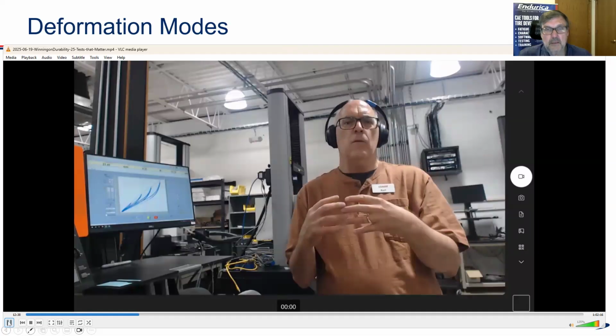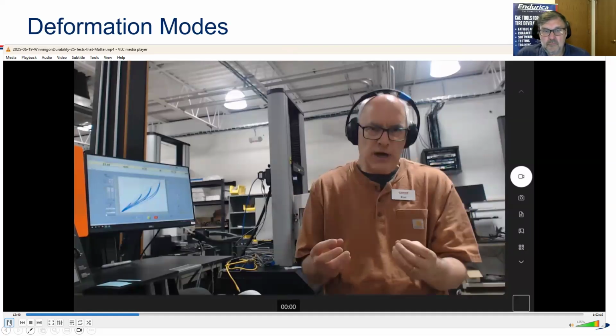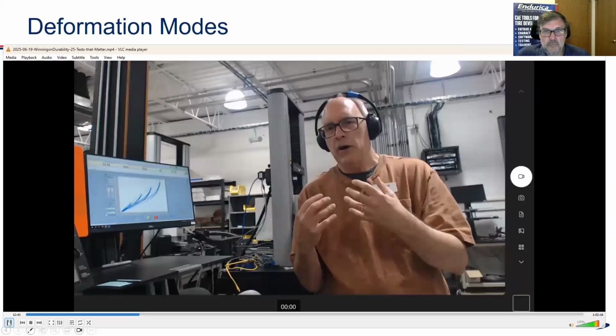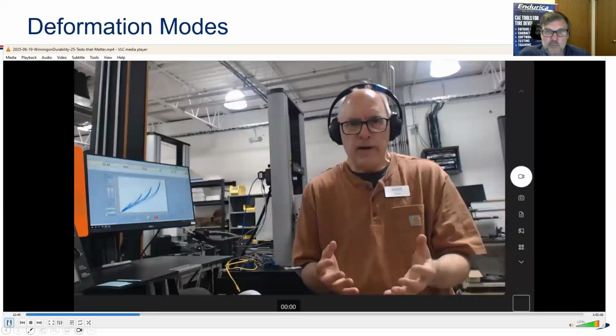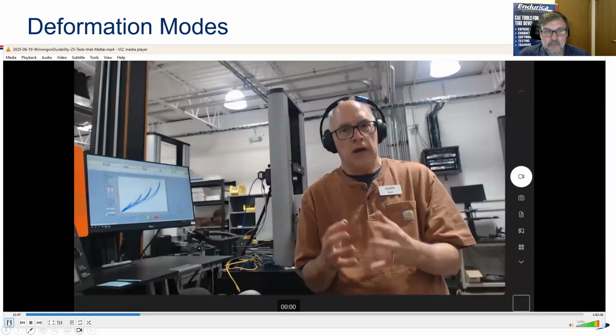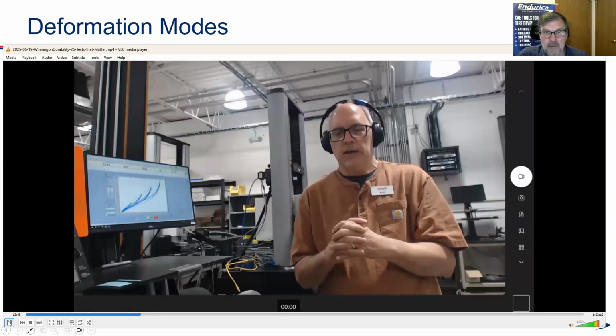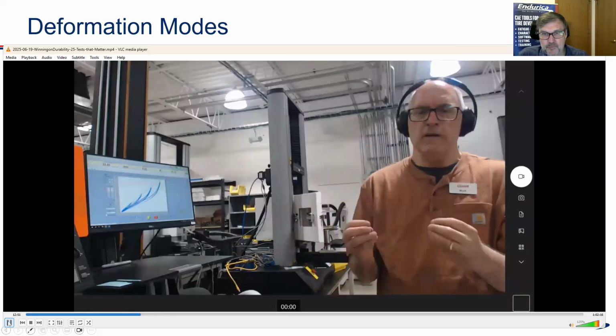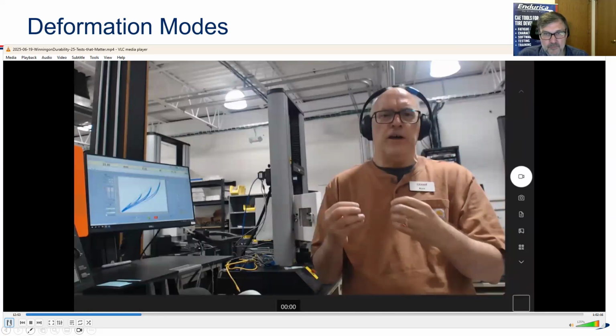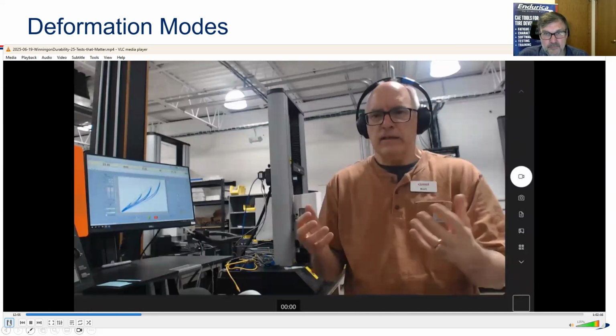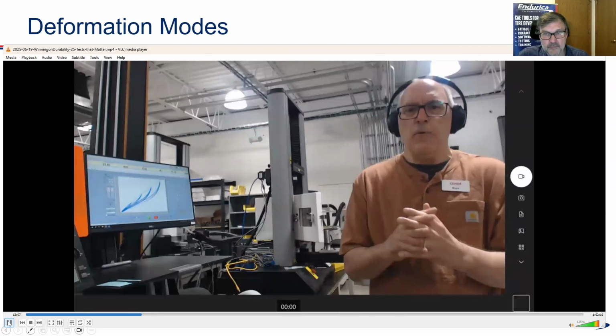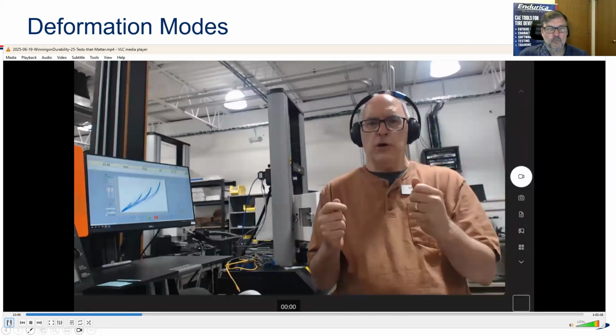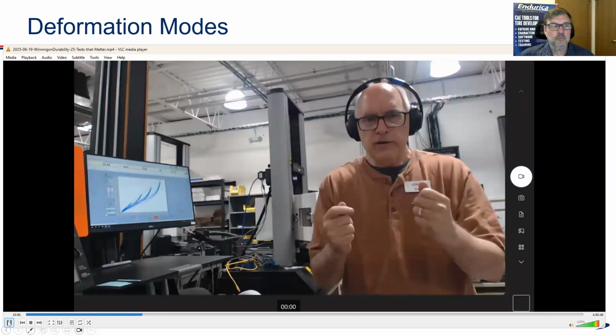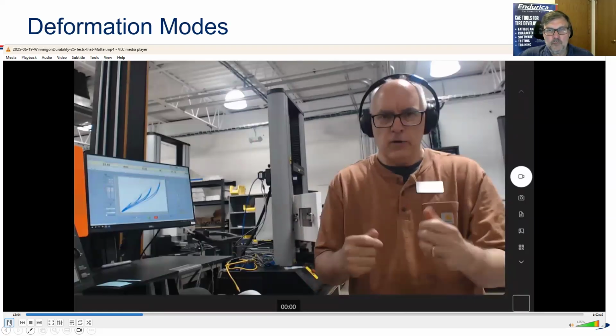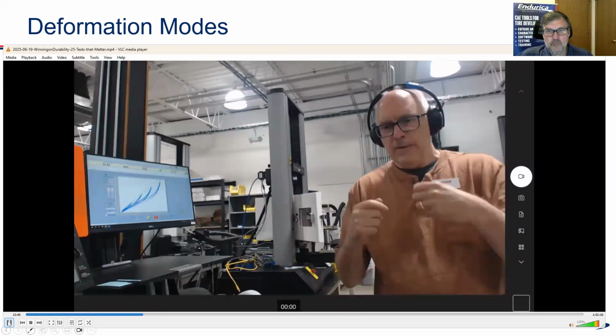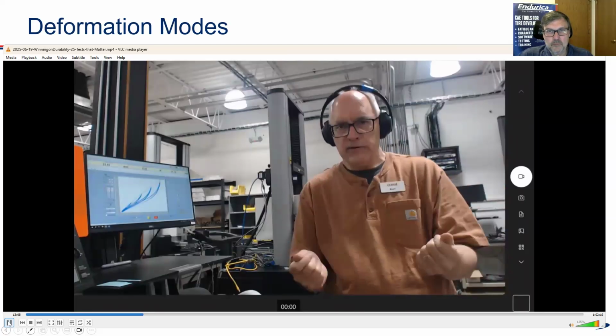And because we care a lot about high strain and high stress points where fatigue or failure may happen, we really want to have great hyperelastic material models. And so we're going to do experiments. Now, these experiments are a little different than plastic and steel experiments, in that what we're trying to do is put the elastomer in a particular state of strain so that it can be described with a closed form math solution.